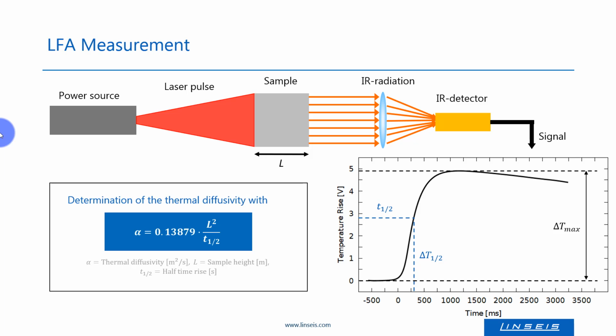The norm describes the experimental setup in detail, which is schematically shown on this slide. It consists of a neodymium YAG laser, which is used to heat up the backside of a sample using a very short heating pulse, and an infrared detector with a high-speed data translation card in order to detect the temperature rise on the front side of the sample and measure the time it takes for the thermal wave to conduct through the sample.